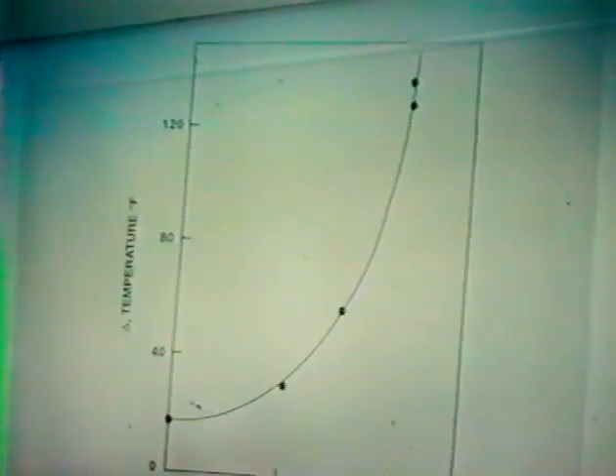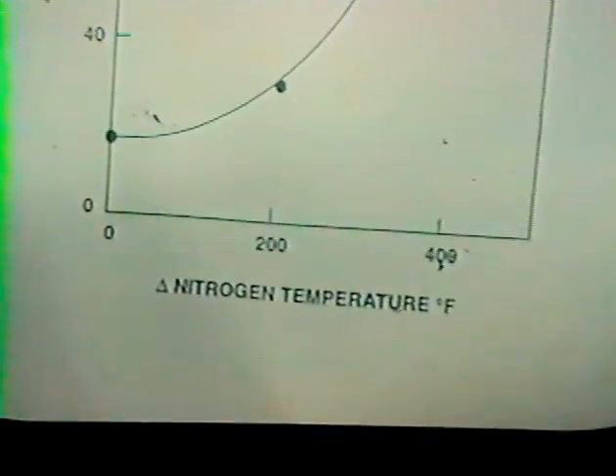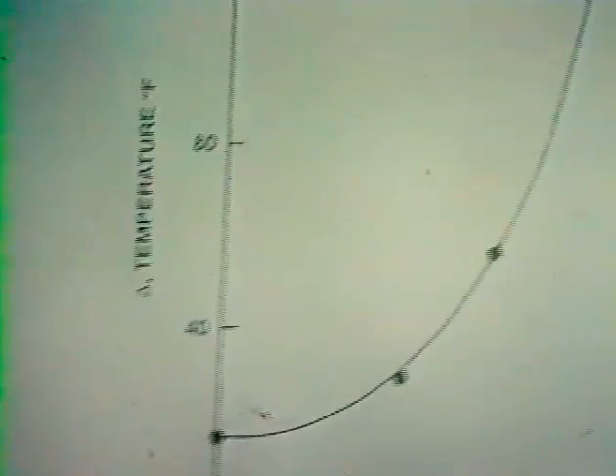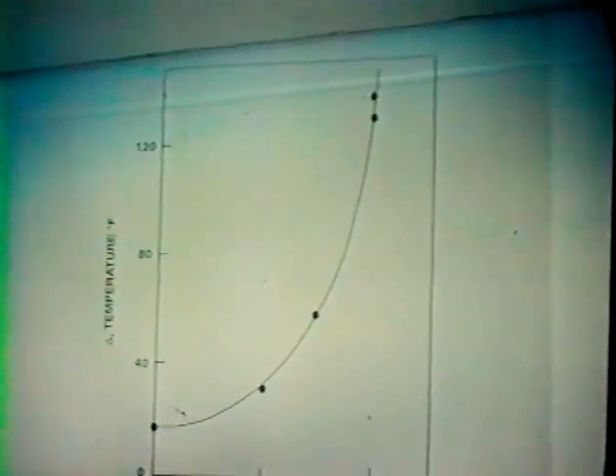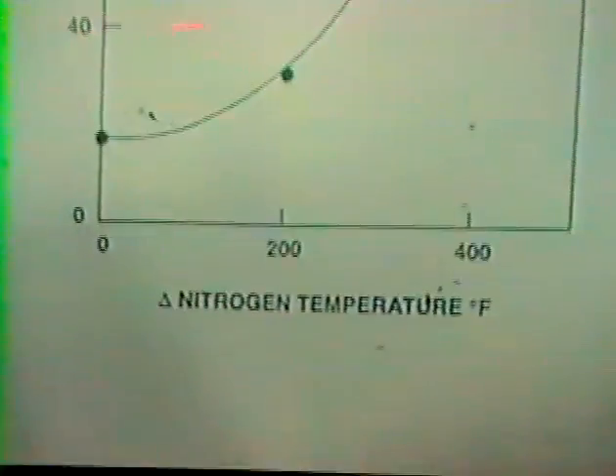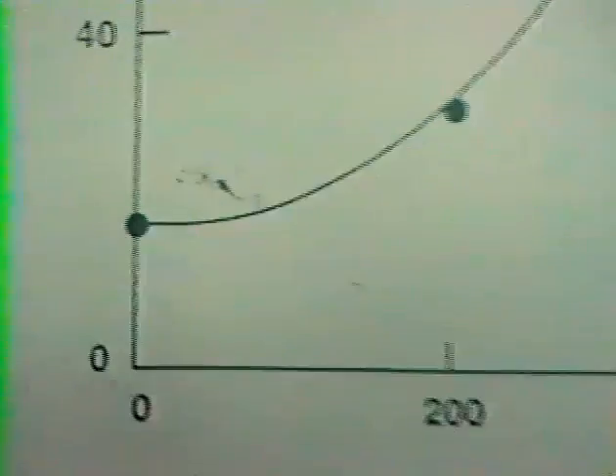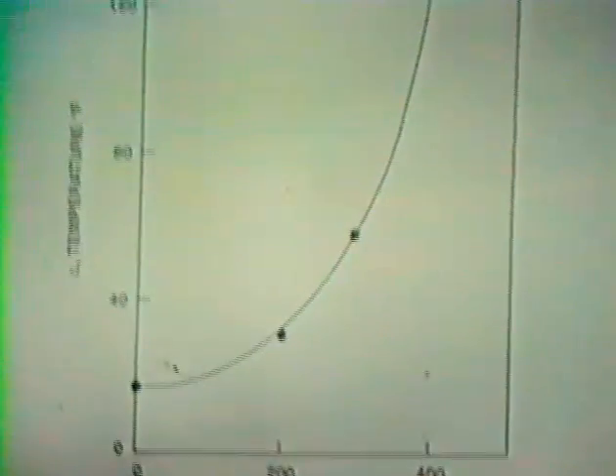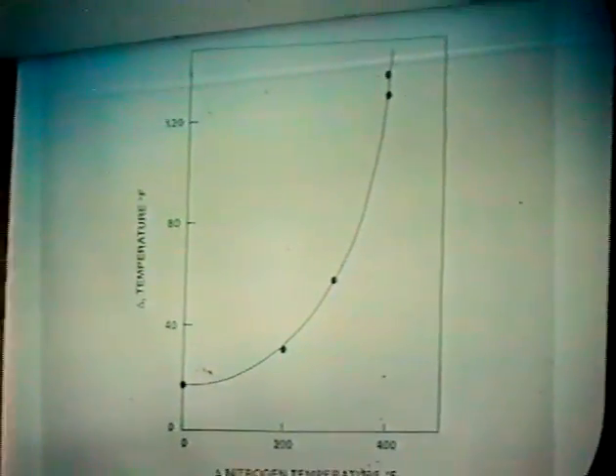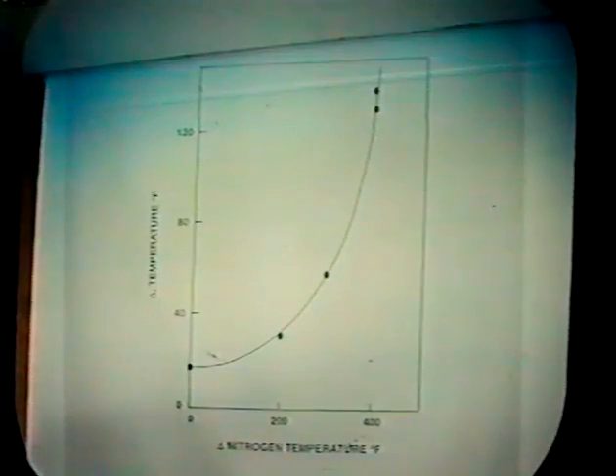Somewhat more confusing to us, if we take the catalyst in the oxide form and place it in the catalytic reactor and heat the catalyst in the presence of nitrogen at 200 pounds PSIG pressure at different temperatures, we see a startling increase in the activity. The activity increase gets up to over 120 degrees. Well, it's heated 400 degrees F for about 6 hours. This phenomenon does not occur in helium. It does not occur if the catalyst goes from the oxide form directly to the reduced form treated with hydrogen.